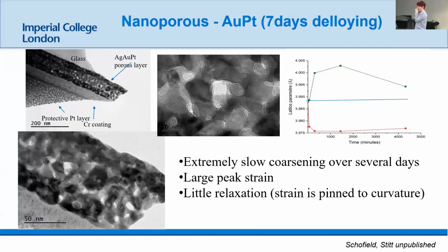Okay, so why is that interesting? Apart from understanding the mechanical properties of the nanoparticles, well, strain in surfaces does more than control the mechanical properties, right? Especially when you're in a metallic surface. If you think about having a strained interface, you've changed the local chemical potential. You've changed potentially the electronic contribution. You will change the plasmonic response.